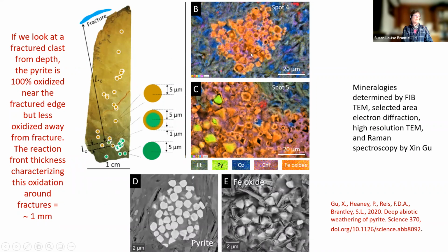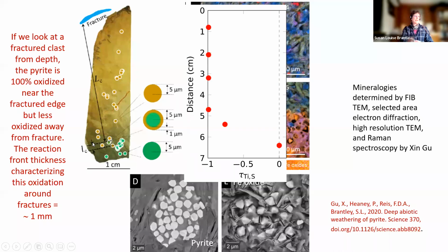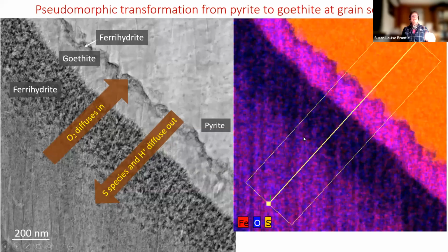And you can see these over here. So here's the completely oxidized little pyrite grains. And then here's partially oxidized pyrite grains, showing you that the reaction front is like a millimeter in thickness. So here's the reaction front at this scale. And here it's like a millimeter in thickness. The oxidation has advanced 6 centimeters, and the reaction front is like a millimeter.